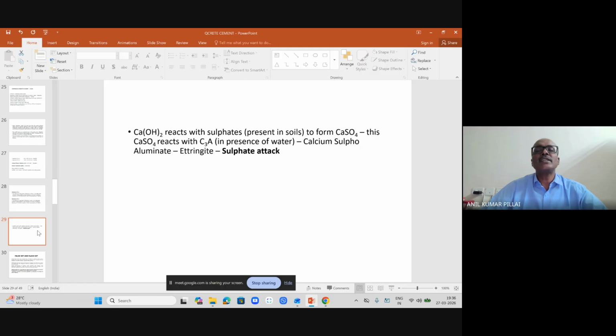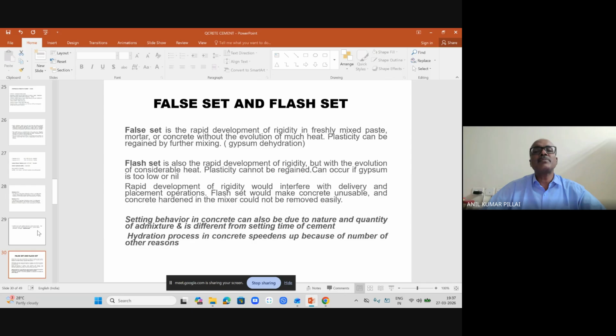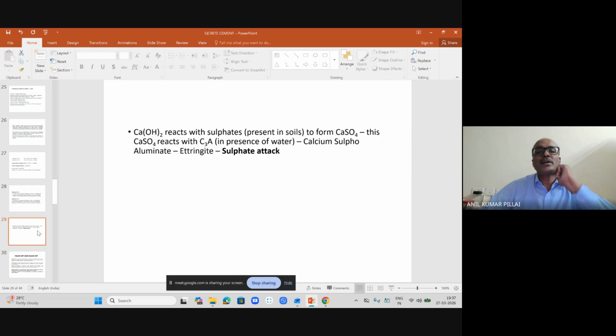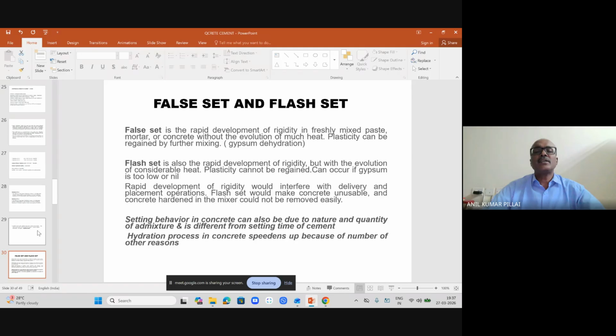So that is why, when the sulfate attack is predominant and you don't have any chloride attack, you can go for sulfate resisting cement, where your percentage of tricalcium aluminate can be brought down substantially, so that it becomes an SRC cement. So basically the mechanism of sulfate attack is like that, and in sulfate resisting cement, we try to decrease the percentage of this one, C3A.